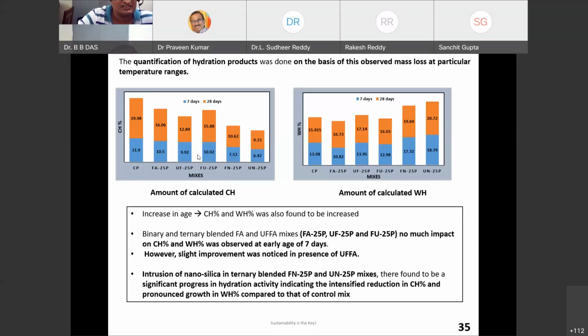Fly ashes reducing, all are reducing actually. Now if you compare with the control, with the fly ash mixes and the nanoparticle mixes, there is a drastic reduction in the calcium hydroxide. Well, we know that calcium hydroxide is responsible for the permeable porosity. Remember, your permeability is dependent on how much percentage of calcium hydroxide is generated in the hydration process. So what is happening here? Well, this percentage of calcium hydroxide is drastically reducing by adding a very small percentage of nanoparticles.